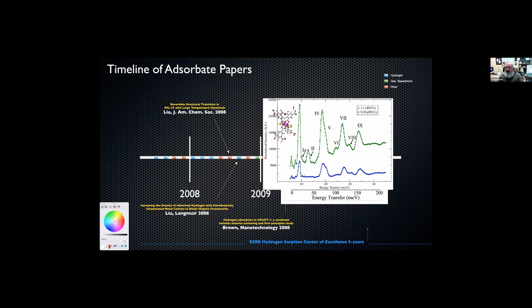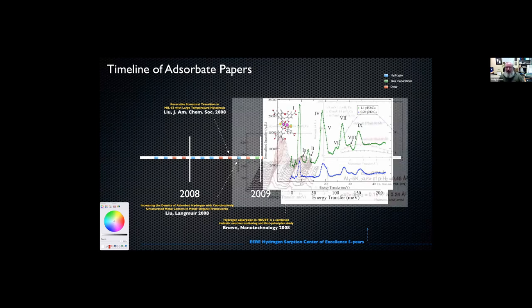The blue curve at the bottom shows what we measure with less than one hydrogen on the metal center, and the green, there's more than one hydrogen on the metal. So we're occupying at least two sites, even if there's a distribution between the different enthalpies for the different sites. If we focus on the blue parahydrogen, if you expect a J equals zero to J equals one transition, if it's ideal, then that energy is about 14.7 meV, right? Clearly it's not that. If the hydrogen's interacting with a surface, then that J equals one level splits into two or three different manifolds. And clearly there's more than three transitions here. And so the goal of this paper was to try and understand why that's happening.